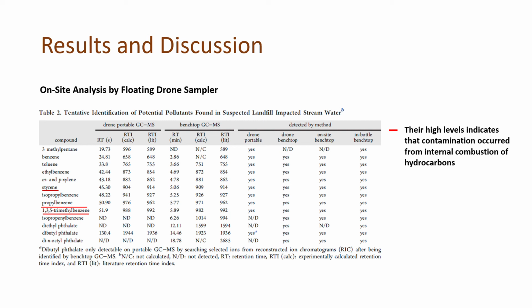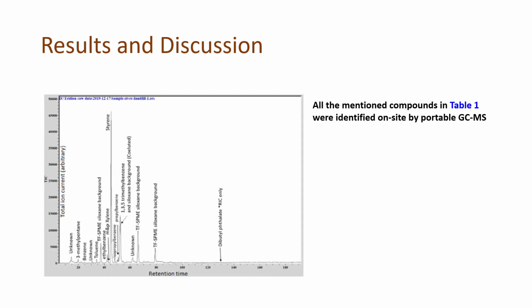Most importantly, it should be noted that high levels of styrene, 1,3,5-trimethylbenzene, and propyl benzene indicate contamination originating from the internal combustion of hydrocarbons, such as diesel and gasoline, because the proximity of the highway to the sampled watercourse gives a probable source of this contamination. All these compounds could be immediately identified using the on-site GC-MS instrumentation after the thin film solid phase microextraction sampling. So it is a good indicator of the potential impact of this method.